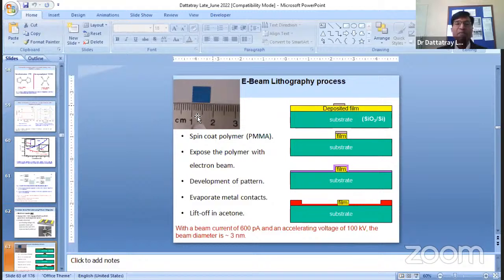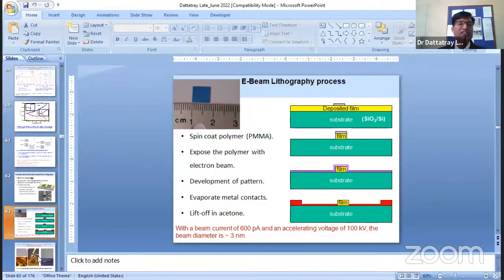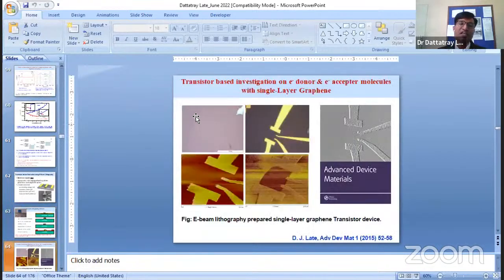And how can we make a device? This is a simple procedure. We can get it from any research paper on the internet, how we can use electron beam lithography to fabricate this kind of device. And then once the device is ready, this is an optical microscope image of single layer graphene transferred on SiO2. This is the optical microscope image after fabrication, and this is the SEM image, and these are AFM images of the device you can see. And these are again field effect transistors based on single layer graphene.